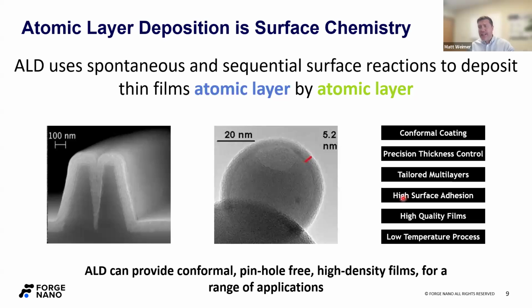Talked about surface adhesion already, but I think this is sort of a good place to talk about this middle image. We do a lot of powder and particle ALD here at Forge Nano. So we have this cool image of a roughly 50 nanometer particle with about 5 nanometers of ALD. And it's pretty apparent from the image that there's no cracks, there's no pinholes. You get a nice uniform 5 nanometers all around it with good adhesion. So from a film quality perspective, I just really love this image. It really highlights it. And for those of you that aren't familiar, typically ALD happens below 300 C. There are a few processes for nitrides that drift up higher, but typically ALD is considered a low temperature technique.